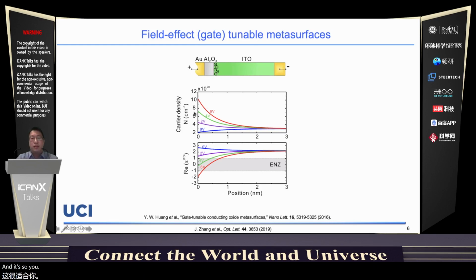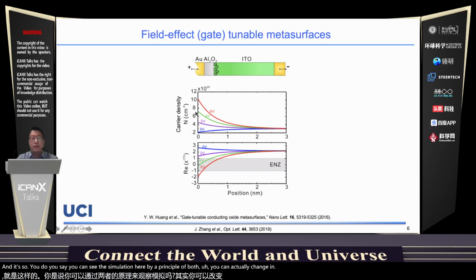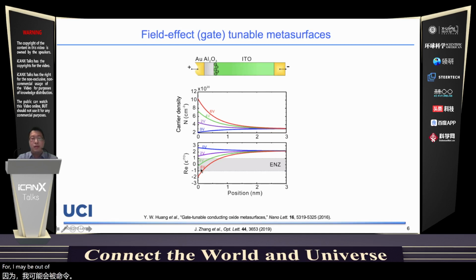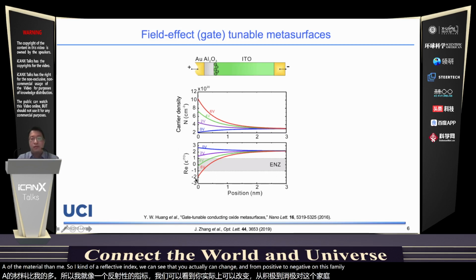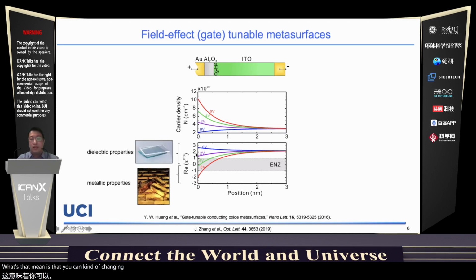And to show you this, you can see the simulation here: by applying a couple of volts, you can change the carrier density by maybe an order of magnitude. At the same time, if you look at the permittivity of the material, that means the refractive index, you can see that you can change it from positive to negative. What that means is that you can change from a dielectric property to a metallic property just by applying voltage here. So you can see that's really impressive. You can apply the voltage and tune the optical property really efficiently. And this is how we're using this mechanism to make a tunable metasurface here.